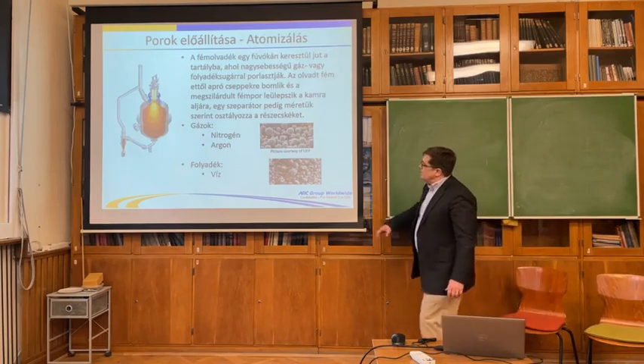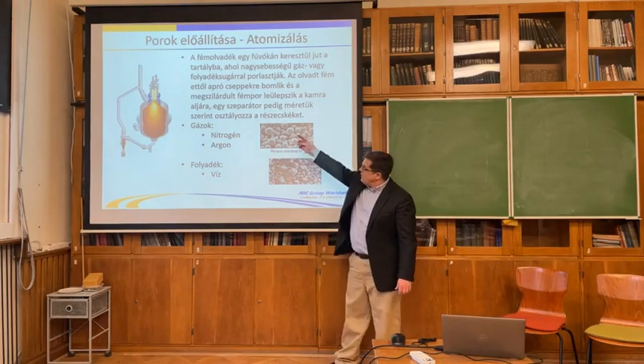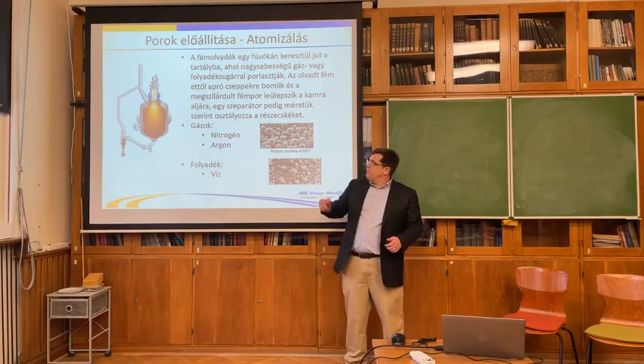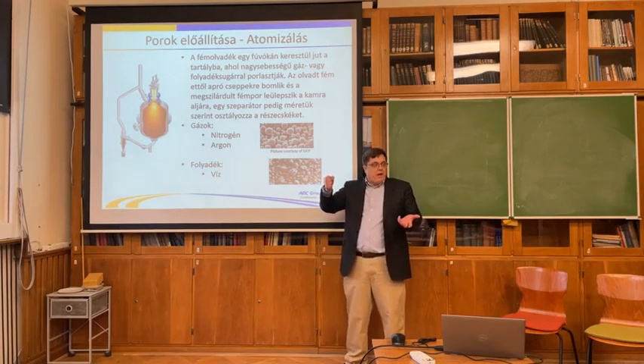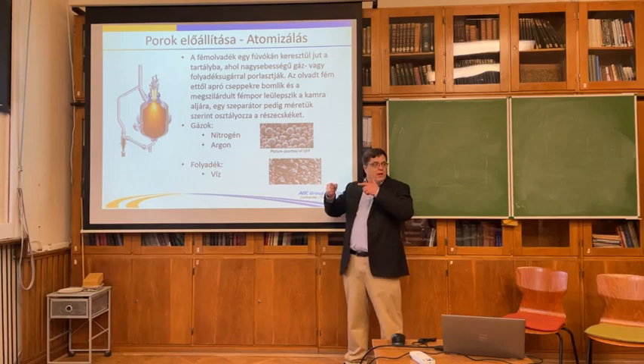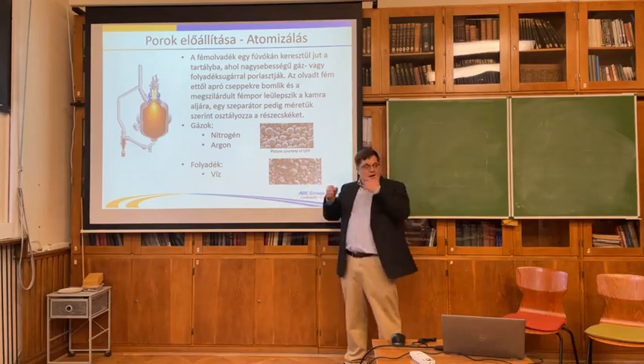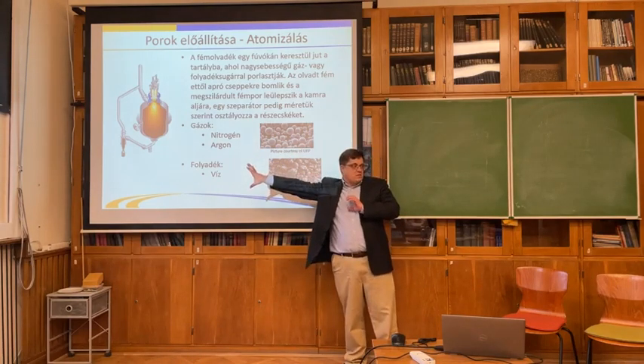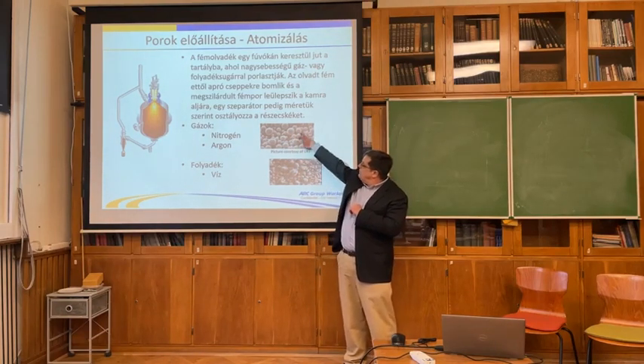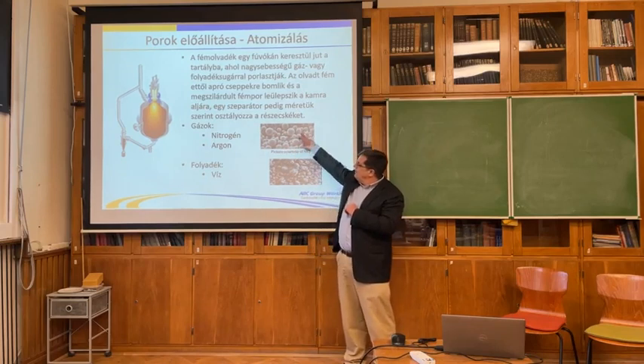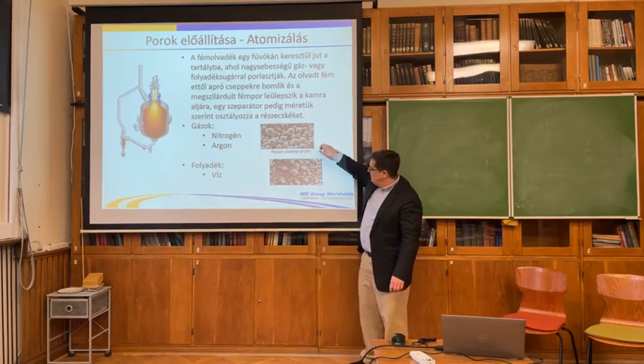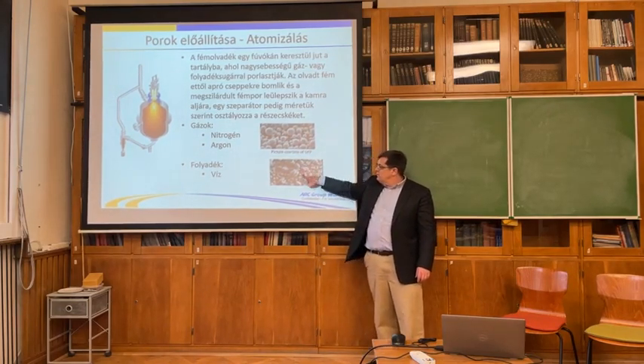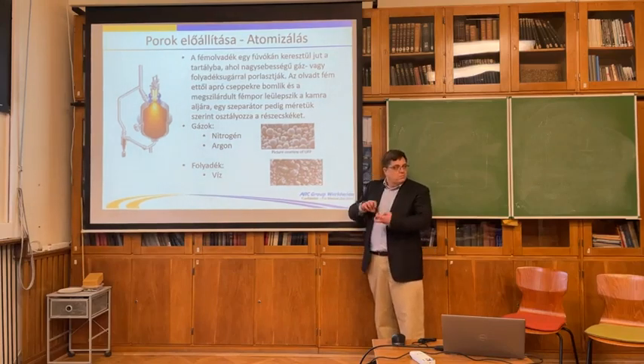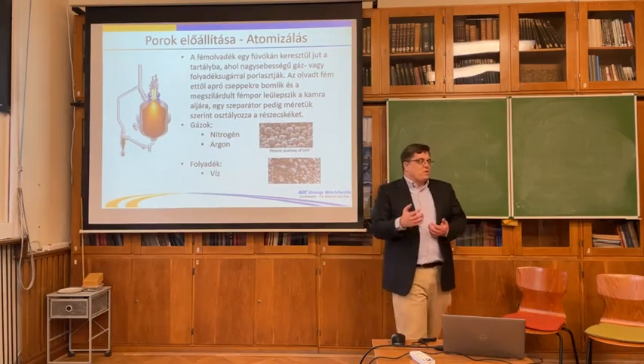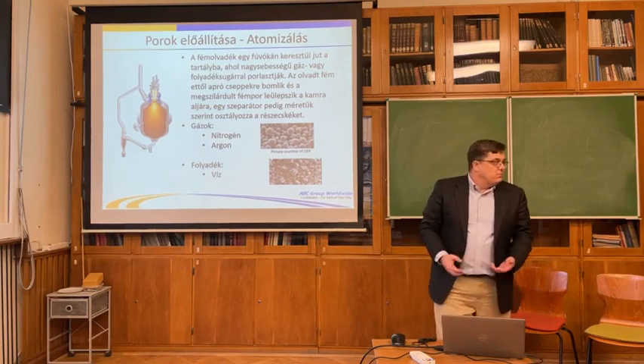So this slide is showing that when they do gas atomized, they're heating up a block of steel and blowing gas, either argon or nitrogen, at high pressure across it, and that's creating a stream of particles, and they classify the particle size. You can see in here, very spherical particles, but with the water atomized, they're much rougher. So there are advantages and disadvantages to both.